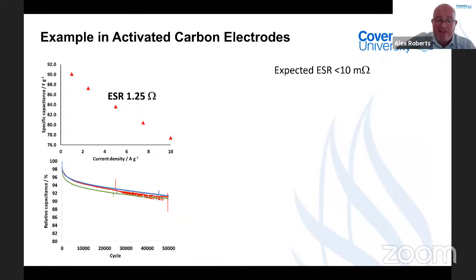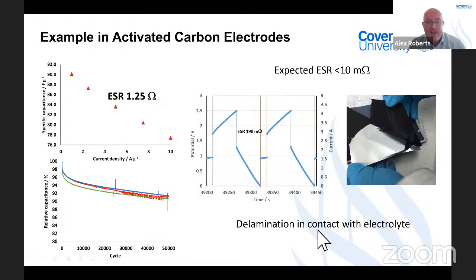We go through all these stages. And then it came to making, I think it was around 75 meters of electrode, weeks of hard work to make the cells, and you put them on to test. And it was a disaster. So you can see here straight away, you can imagine my horror when the testing came up and I was out by a factor of nearly 20 in my series resistance.